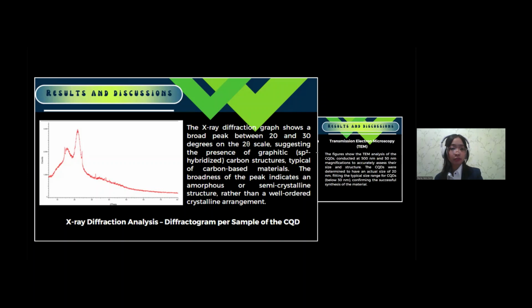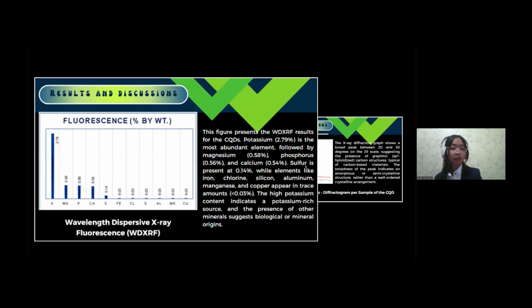showing mixed structures. This kind of structure is common for carbon quantum dots and helps improve their optical and photoluminescent properties, making them useful in sensors and imaging. The amorphous nature also explains the high surface area seen in the FESEM images, as these materials usually have irregular porous surfaces. Now, the last test for the CQD characterization was the wavelength dispersive X-ray fluorescence.